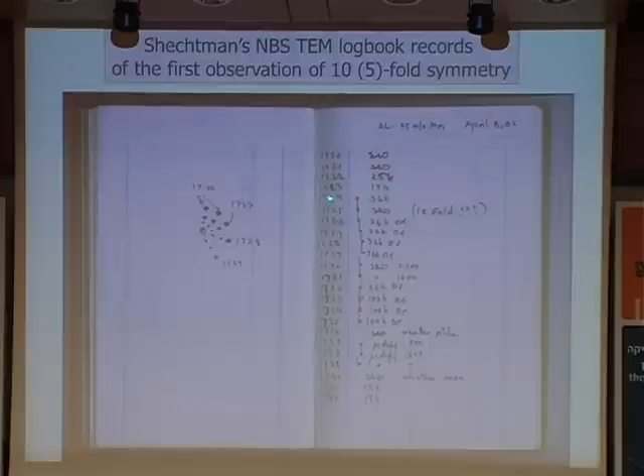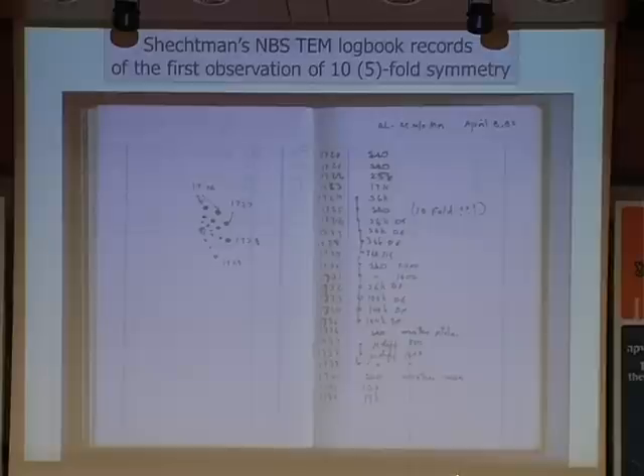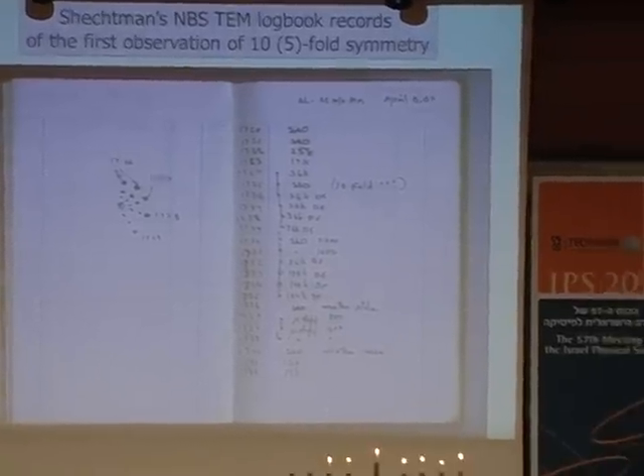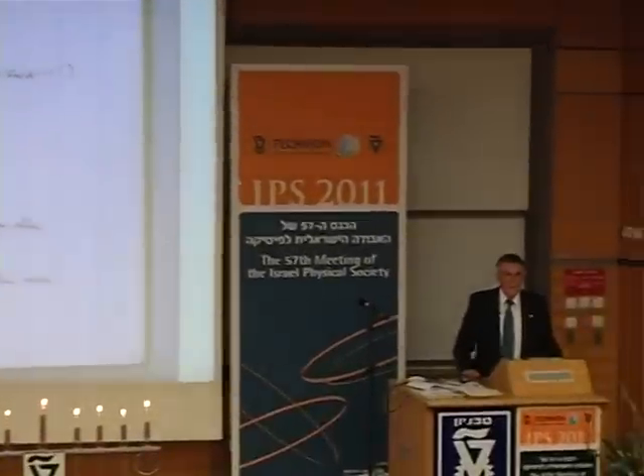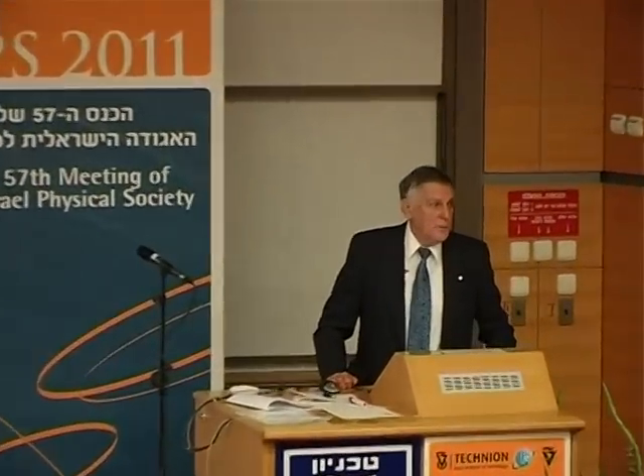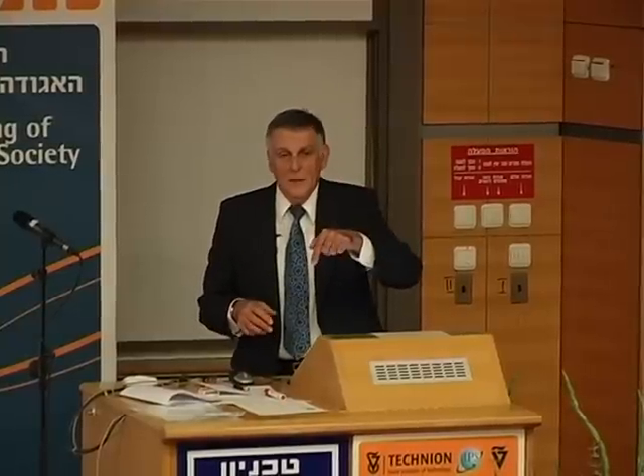And then this plate, number 1724, 36K, and then I saw something very interesting, and what I saw I will show you in a minute. What I saw were crystals in the specimen that were extremely dark. When you see a crystal which is extremely dark, either you do not know how to prepare a specimen for the electron microscope and it's so thick that the beam doesn't penetrate, but that's not me. Another reason could be that that crystal diffracts heavily. So the transmitted beam has very low intensity.